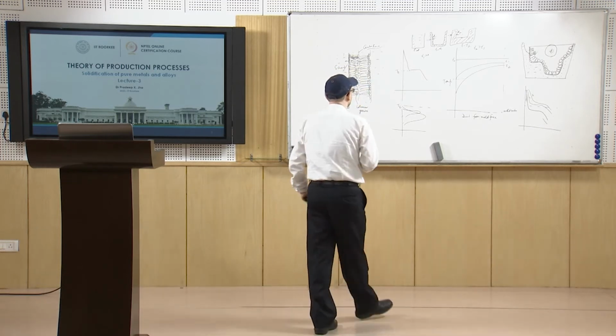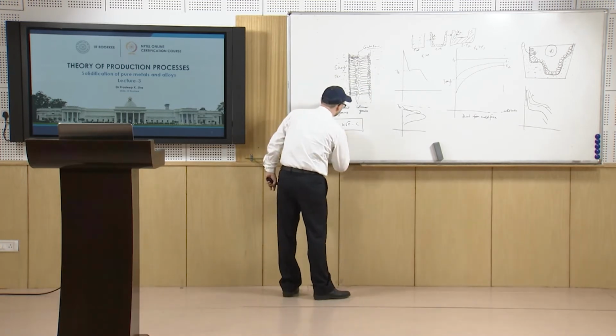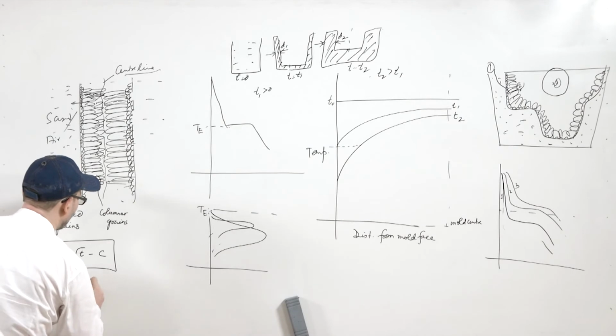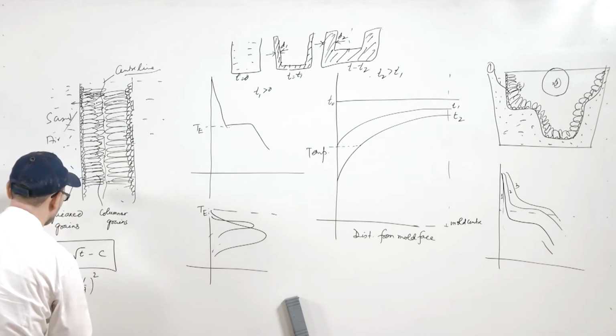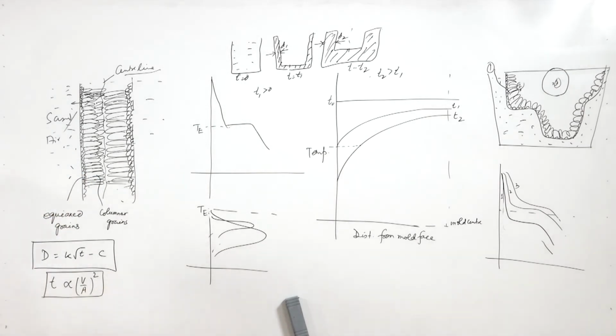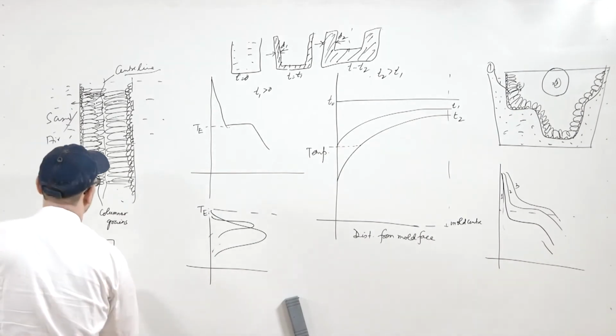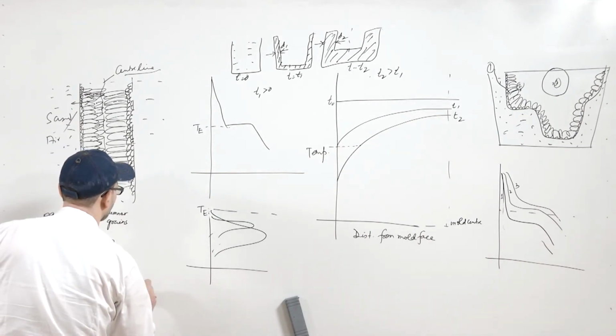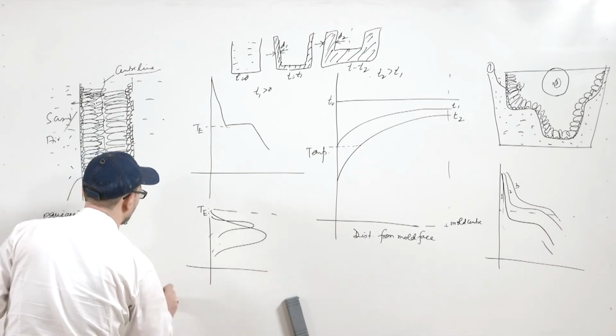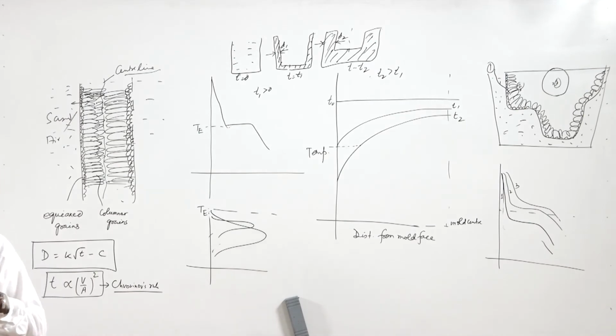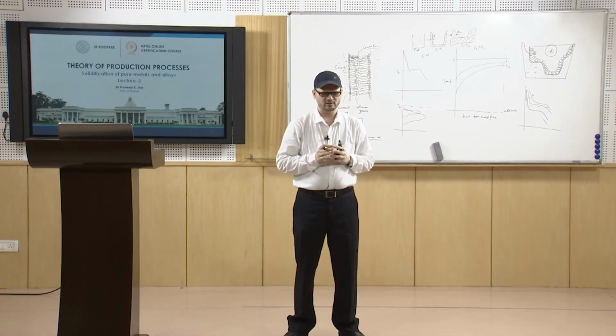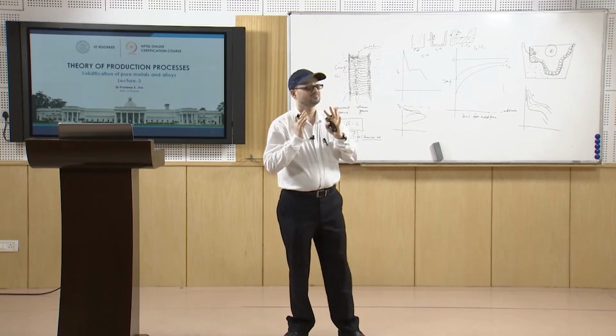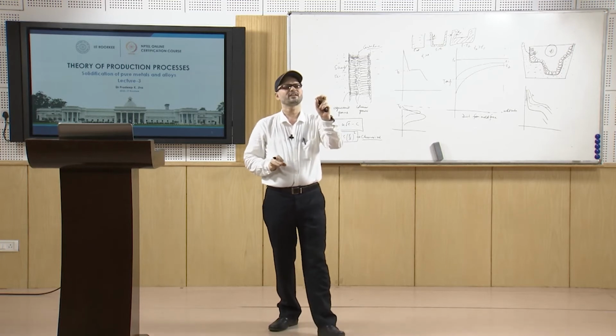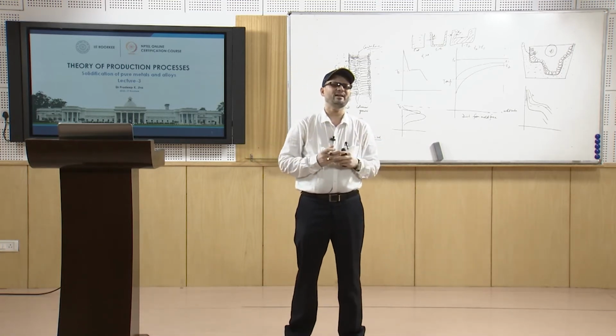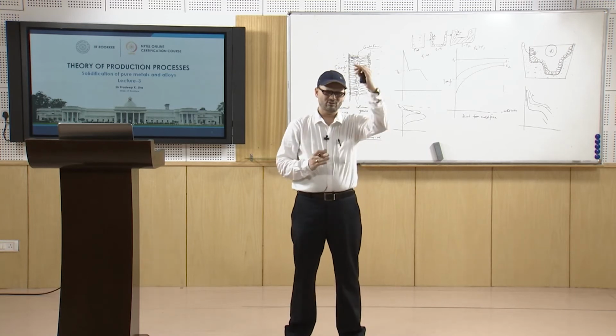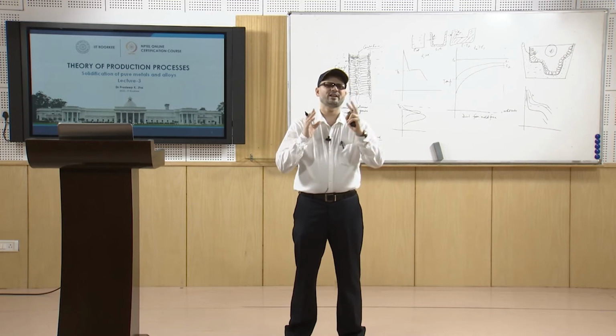That rule is known as the Chvorinov's Rule. So, this is proportional to (V/A) squared. This is something about the solidification of pure metals, where the metal freezes at a constant temperature, or it may even be applied in the case of eutectic composition, where the freezing is carried out at a constant temperature.